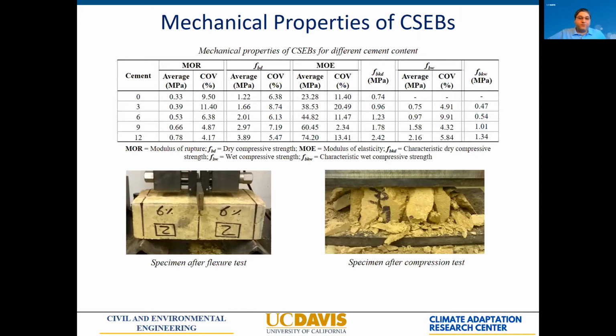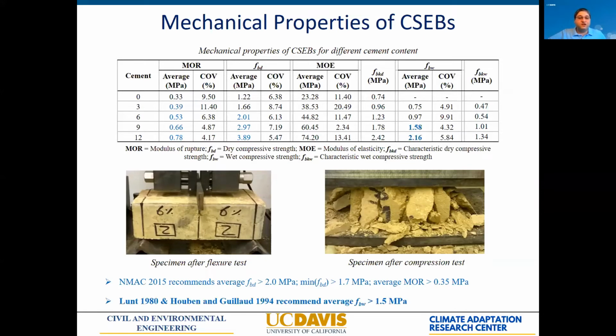We found that in terms of compressive strength, we are able to achieve enough strength already with 6% cement. And then when we investigated the durability and the performance under wet conditions, we needed to have a little bit more cement, so that at the end our solutions included 9% and 12% cement. These are relatively high values of cement, and that is really because the soil available locally was not optimal for the type of construction that we were considering. But even under that condition, we could still achieve appropriate compressive strength for our material.